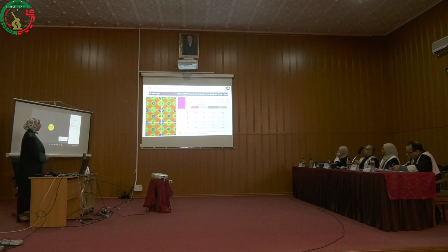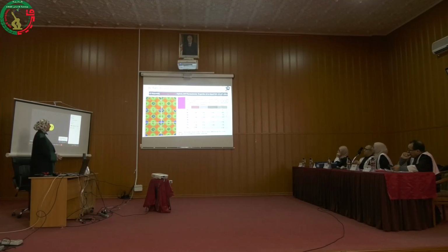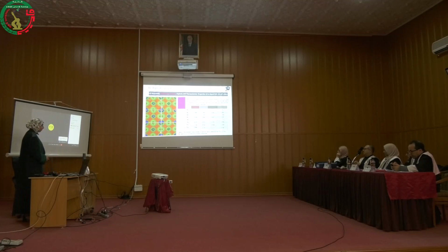Also, in terms of magnetic properties, we have calculated the magnetic moments and exchange constants. The magnetic moments show an enhancement compared to the monodoped compounds, which is a good result, and the most contribution comes from iron and alkali interstitial sites, whereas due to the s-p-d hybridization, local magnetic moments are created on the non-magnetic sites. In terms of exchange constants, the s-d exchange is found to be antiferromagnetic, whereas the p-d exchange is found to be ferromagnetic.